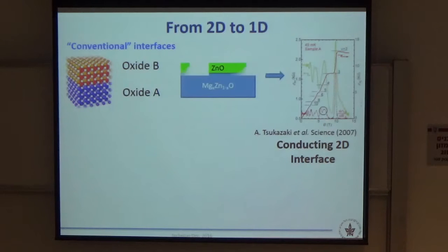Basically, you can etch it away in the lab, and then have a very narrow constriction. And let's say the length scale here is a Fermi wavelength. So basically, if you want to be strictly 1D, you have to make this narrower than the Fermi wavelength. In our case, it's about 1,000 angstroms, or 100 nanometers, depending, of course, on carrier density.